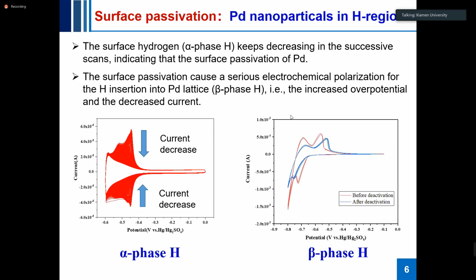And the blue line is the same electrode after the surface passivation. We can see that the hydrogen insertion into the palladium moves to more negative potential, and also the current decreased. This is actually caused by the phase change and the structure collapse of the palladium nanoparticles. So this is not good for the high density accommodation of hydrogen in palladium.